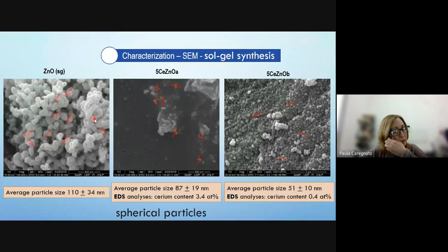These are some images of the scanning electron microscopy of the 3 materials obtained by the sol-gel method. We can see by SEM microscopy the morphology of the solids. All of them present spherical particles, and we can see that the average particle size decreases with the cerium content. By EDS analysis, the cerium content was calculated. For this material, it was 3.4 atomic percent, and for this other material, it was 0.4 atomic percent.